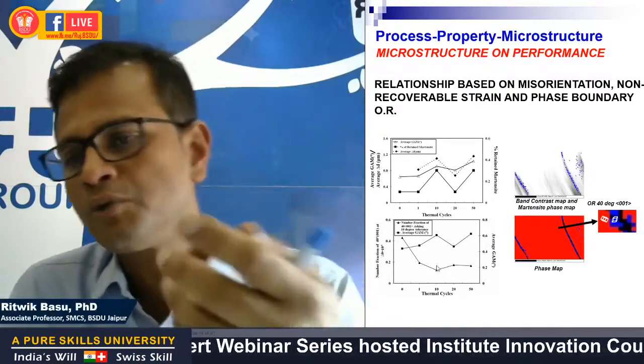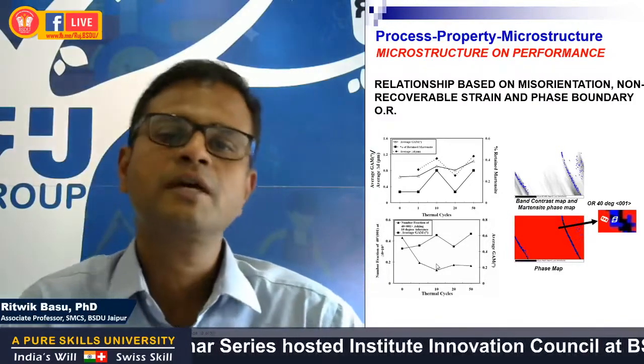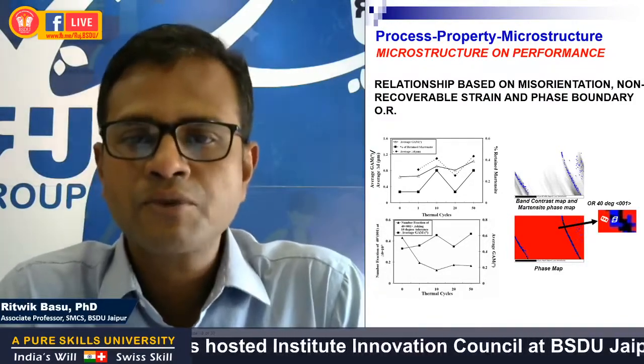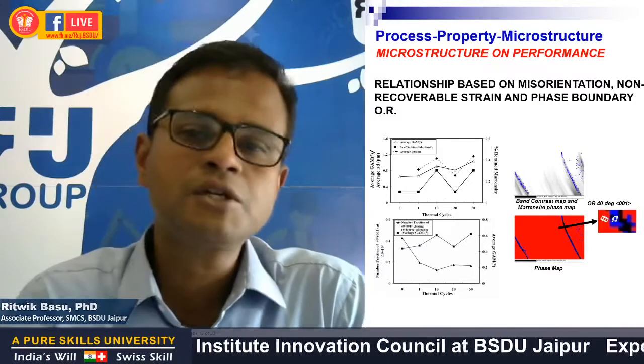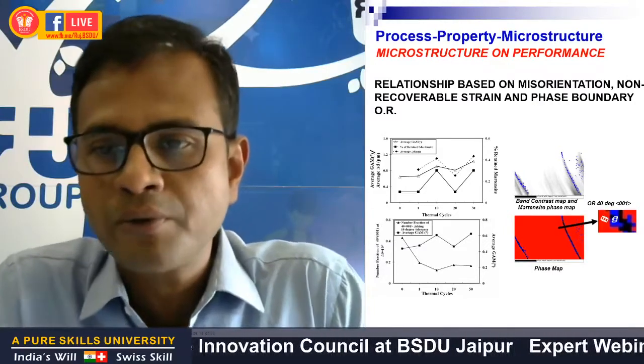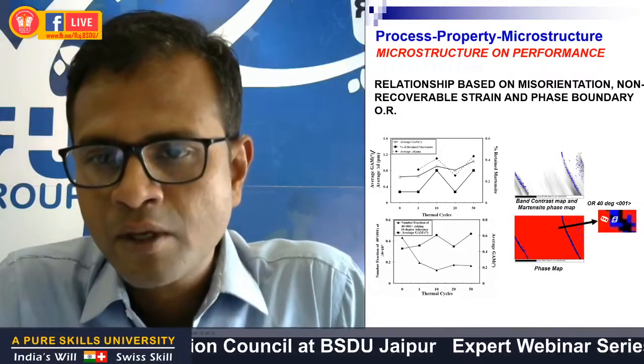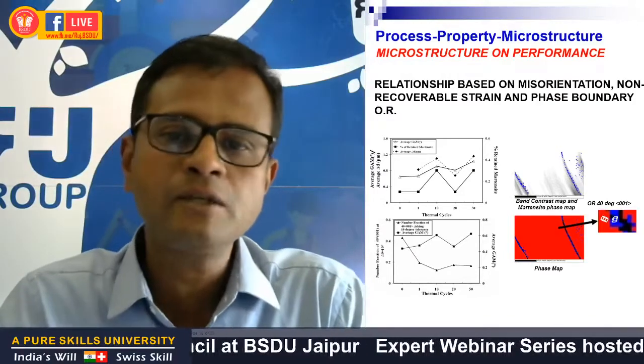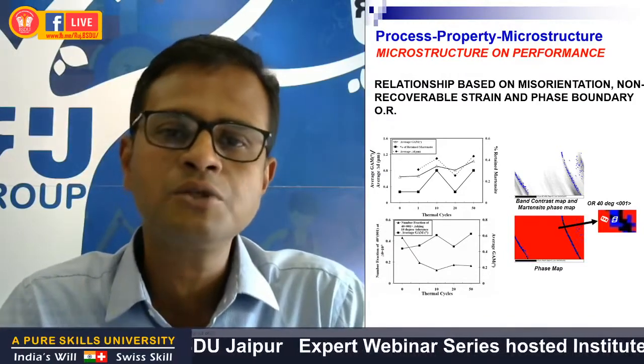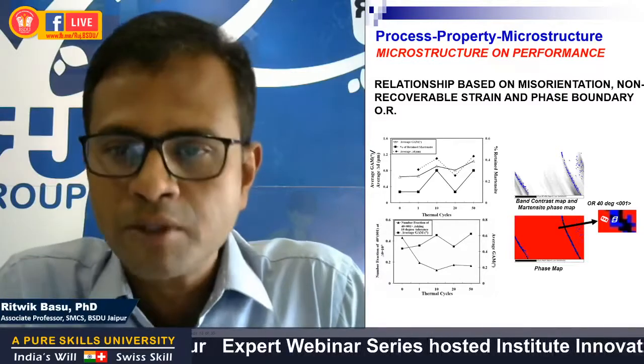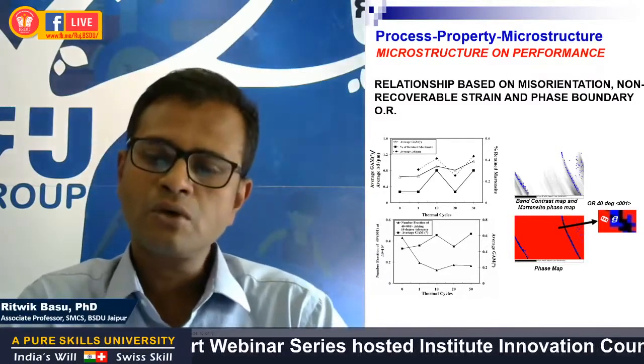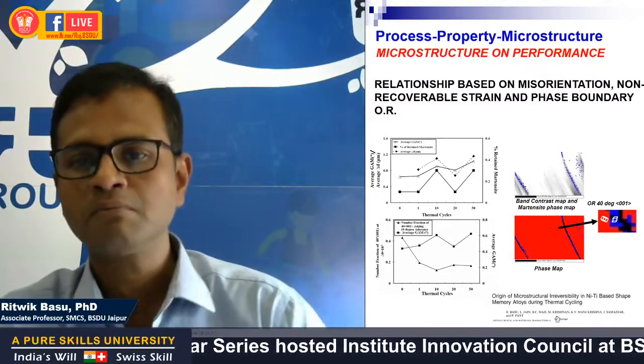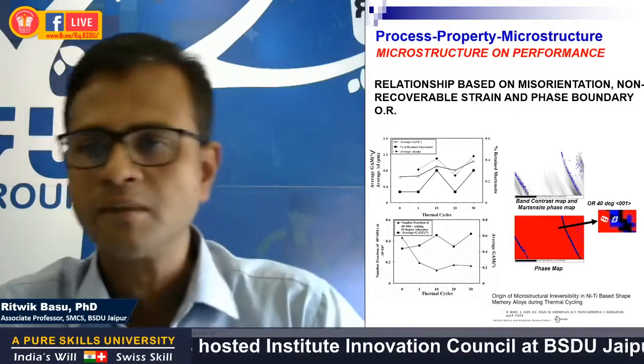So the final conclusion that was made from this study was that the irreversible strain largely depends on the deviation from the exact phase boundary orientation relationship. So any deviation from the ideal orientation relationship will lead to an increase in the irreversible strain. So that was from my earlier research work on nickel titanium alloy systems.